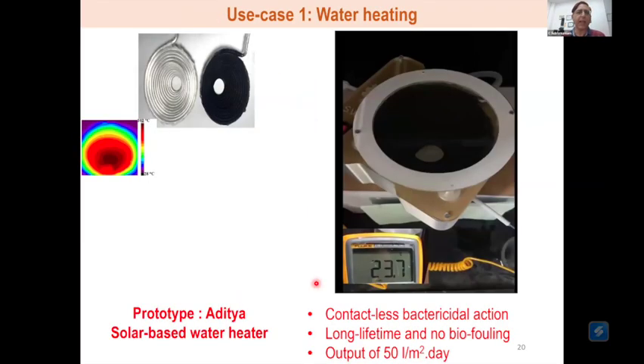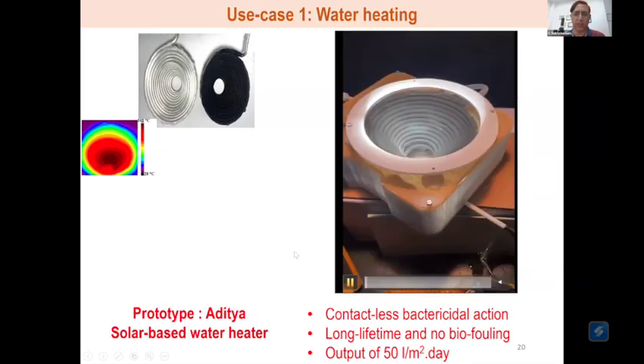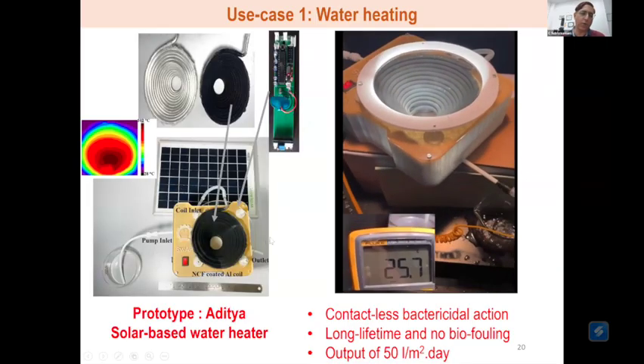And so the first example that we did was take up these hollow aluminum tubes, bend them around in a spiral fashion, and coat the inside of this. The idea is that these are hollow aluminum tubes, so you can flow water through the inside of these tubes, put this in sunlight, and the heat generated by the coating is now able to transfer through aluminum, because aluminum is a good thermal conductor, and we should be able to heat water through that. And that is exactly what this video shows you. We developed a prototype.